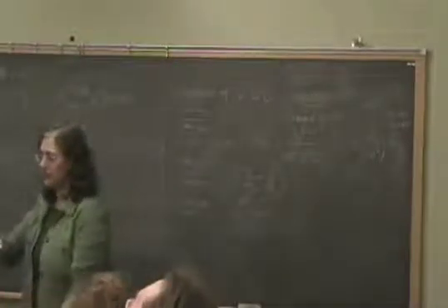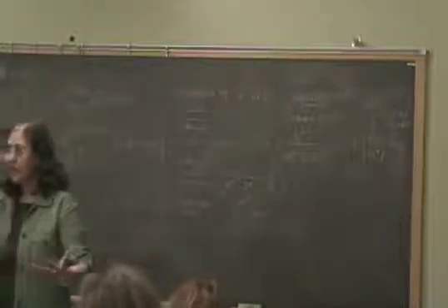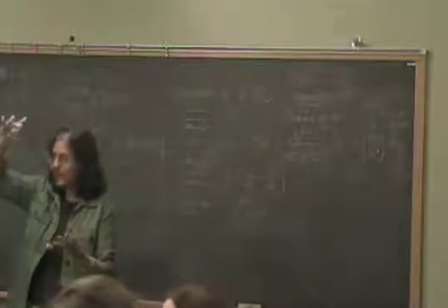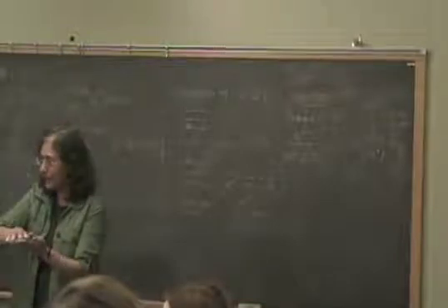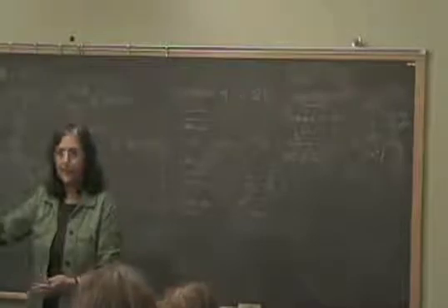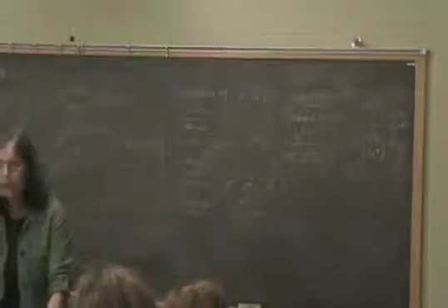Okay, this exciton, think about it. It's a semiconductor dot, or even a bulk semiconductor. You have excited an electron-hole pair, but it's a big object, and it has a binding energy which is also finite, and this is called an exciton. And at some point, this electron and hole can recombine and emit light, and that is called photoluminescence. So people can detect the signal, and from that they can look at the binding energy of such an exciton. And these are the main excitations of a quantum dot.